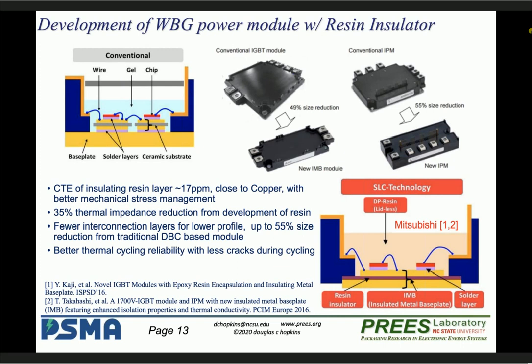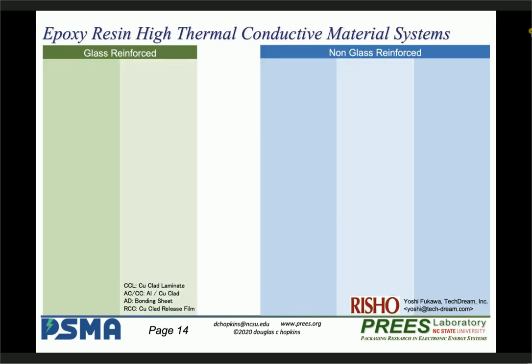Better thermal cycling reliability, less cracks, because the organic is much more forgiving. It's got a much lower modulus, and it depends heavily on the resin interface materials. So here are the resin materials that we looked at, or that we have been supported with. Resonac has been working with us to introduce us to these new materials they've done.